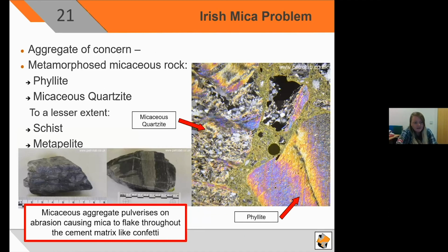And let's go to the Donegal phyllites. So we've got the Irish mica problem, which is usually caused, as we know, by metamorphosed micaceous rock. Typically, this is when the aggregates are used in concrete, and abrasion of these causes them to pulverize and fray like confetti into the binder and become widely distributed. And that's the main cause for concern here.